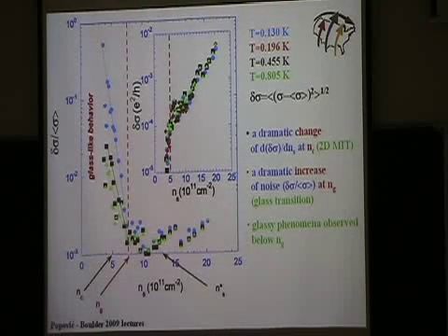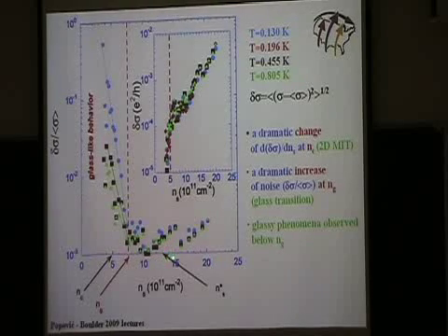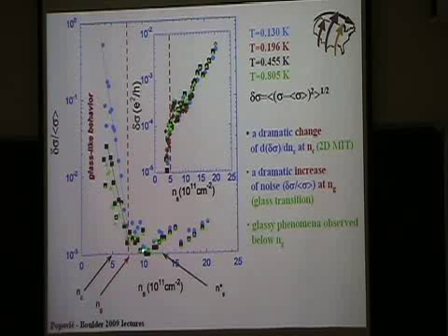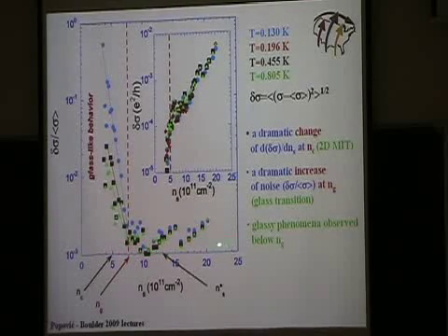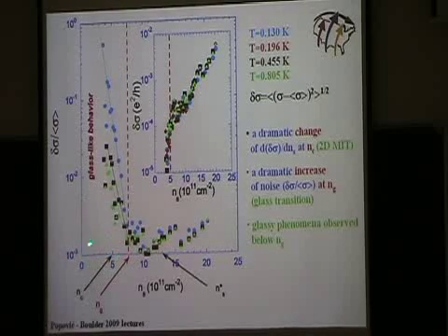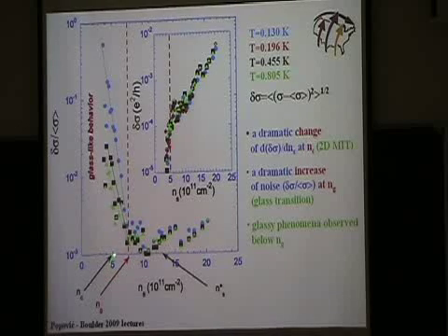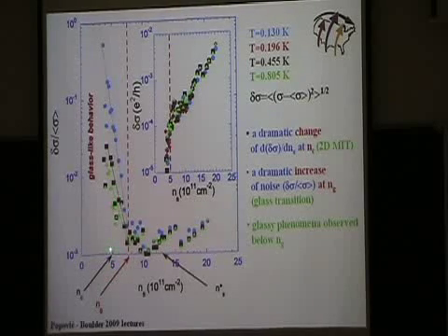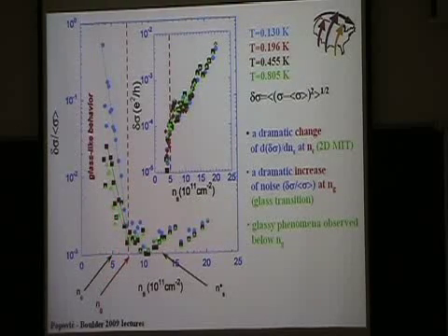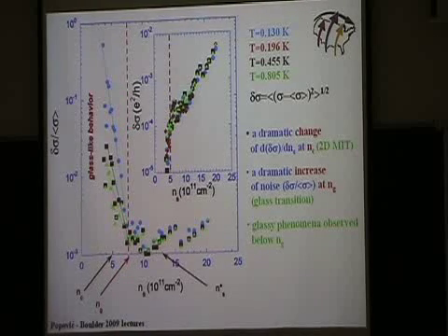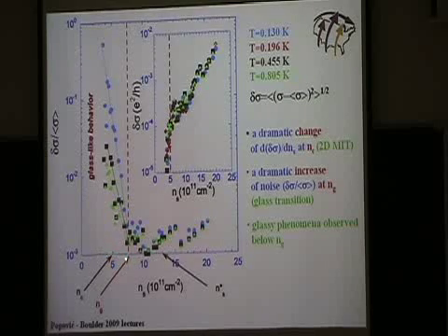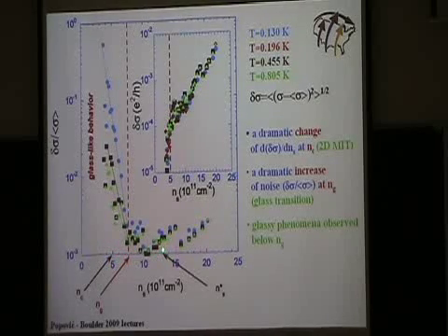So for those of you who remember what I said yesterday, this density is that separatrix, where temperature dependence of conductivity changes sign. This is Ng, where we found that, above Ng, there are no relaxations. Below Ng, we saw these slow non-exponential relaxations, aging, and so on. And then Nc, about 5, corresponds to the critical density for the metal-insulator transition. So we saw this huge increase, but we were surprised that these two densities were not the same, or nothing was happening here.